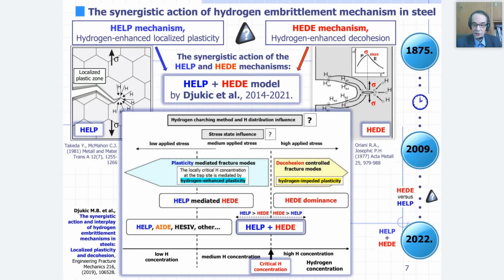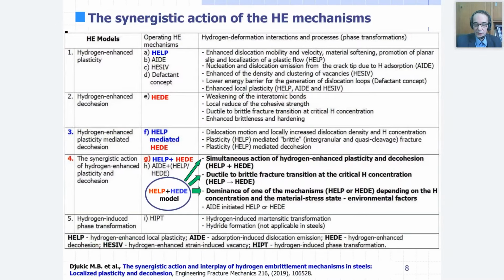while at a high hydrogen concentration above the critical hydrogen concentration we have HEDE dominance, which means that we have opposite effects. We have not enhanced plasticity, but actually hydrogen impeded plasticity, and the activation of the HEDE mechanism, which provokes decohesion controlled fracture modes and typical brittle failure of components, industrial components, and a sharp drop of mechanical properties. So here is the summary.